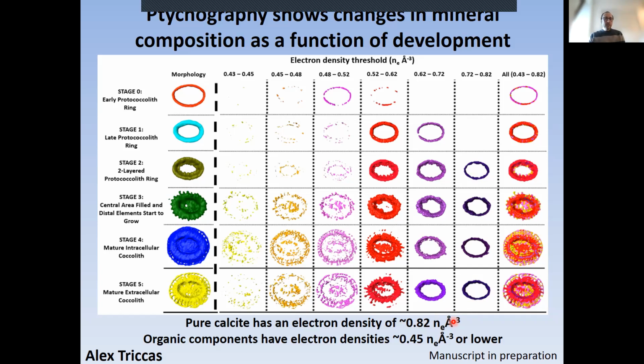And this is the part that was really surprising for us, because when we did the segmentation based on the electron density, we got something else completely. These are 5 or 6 stages of formation based on the electron density. Here you have the morphology of the coccolith at different stages, from proto-coccolith ring to when you start growing the distal and proximal elements, these struts, all the way to the mature coccolith. What is really striking is that in this early stage, we have a ring that is presumably of calcium carbonate, but it's very low in electron density. We're talking about electron density between 0.4, mostly in the ballpark of 0.5 electrons per cubic angstrom, with very few regions a little bit over that, but not going over 0.62.